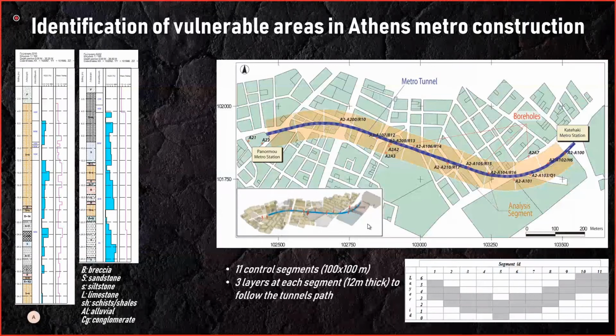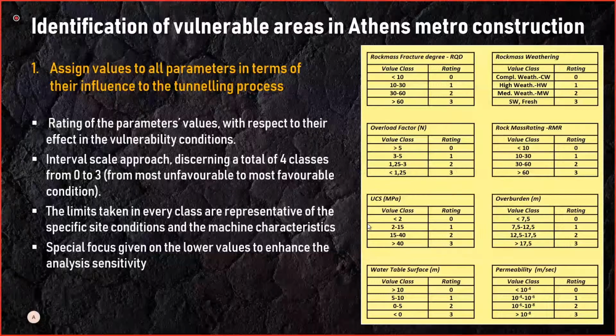Also, in this slide, you can see in light orange color the 11 areas that were used for the analysis. These are the 11 segments, each one of them covering an area of 100 by 100 meters following the TBM's path. Besides this horizontal division, we have also divided the tunneling path vertically in 3 layers, each one being 4 meters thick, so as to cover 12 meters thickness, covering the 8.5 meters diameter of the tunnel. Of course, the next thing to do is to rate the parameters accordingly in order to capture their influence on the tunneling process.